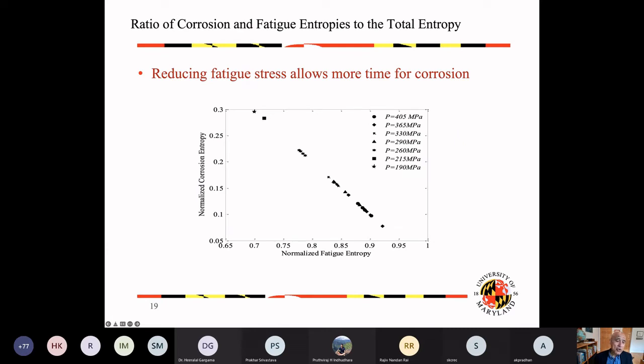And if I were to show you the normalized contribution of the amount of damage due to corrosion versus due to fatigue in a corrosion fatigue phenomenon, you can see that for cases with very high stress, more damage was contributed to entropy. About 90% of the damage, which is 90% of the entropic damage, I would say, the entropy accumulated, was attributed to fatigue. But if the loading was small, which gave much more time for corrosion to work, because corrosion needs time to act and cause damage, then the contribution from corrosion got bigger when the loadings were smaller. That's what we were expecting, of course.